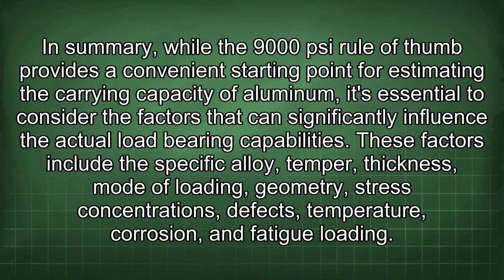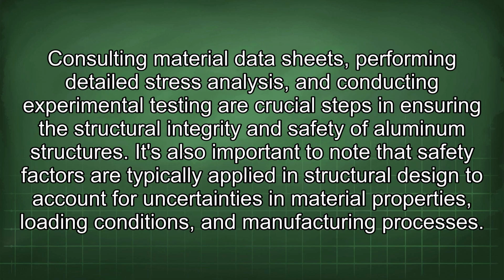In summary, while the 9,000 PSI rule of thumb provides a convenient starting point for estimating the carrying capacity of aluminum, it's essential to consider the factors that can significantly influence the actual load-bearing capabilities. These factors include the specific alloy, temper, thickness, mode of loading, geometry, stress concentrations, defects, temperature, corrosion, and fatigue loading. Consulting material data sheets, performing detailed stress analysis, and conducting experimental testing are crucial steps in ensuring the structural integrity and safety of aluminum structures.